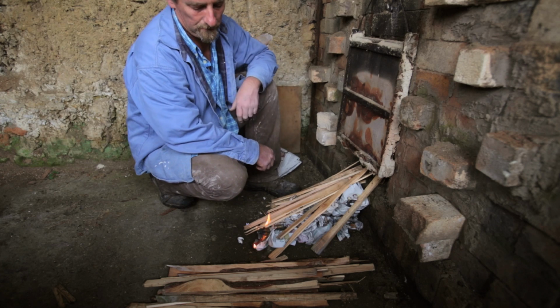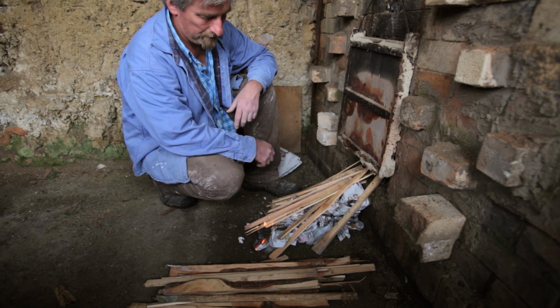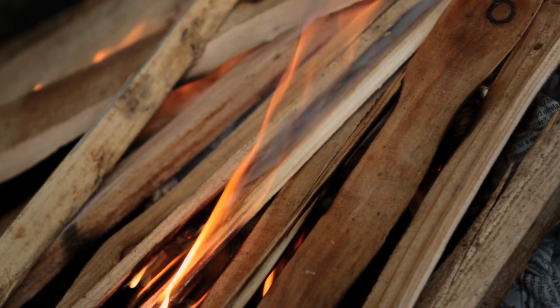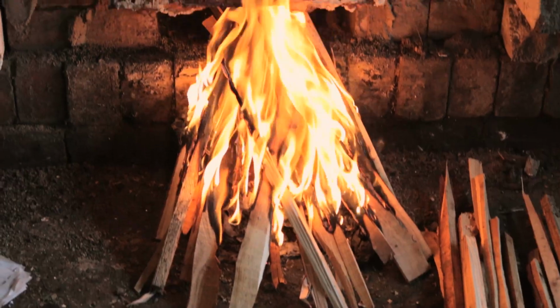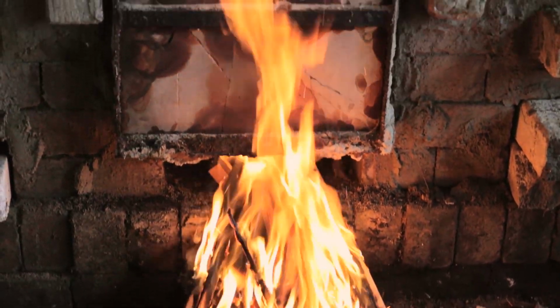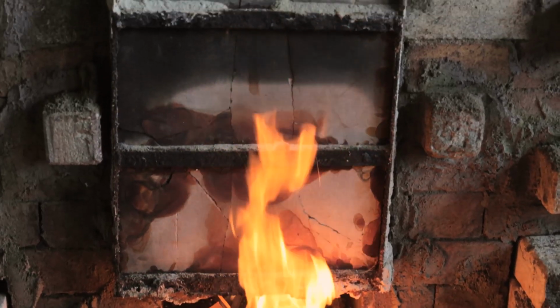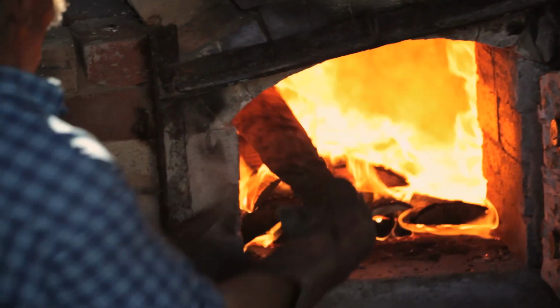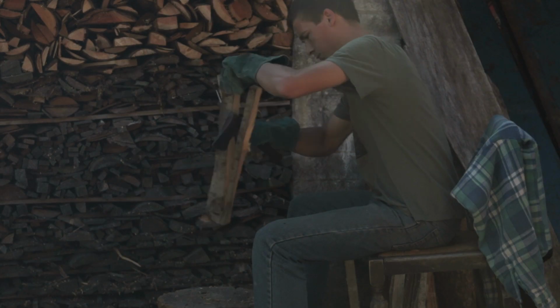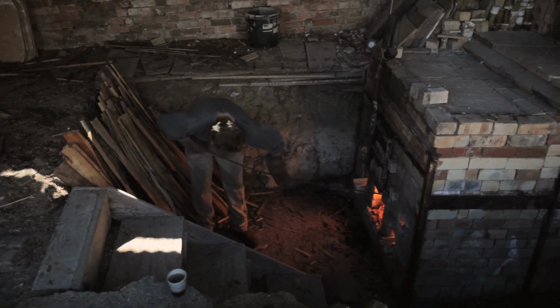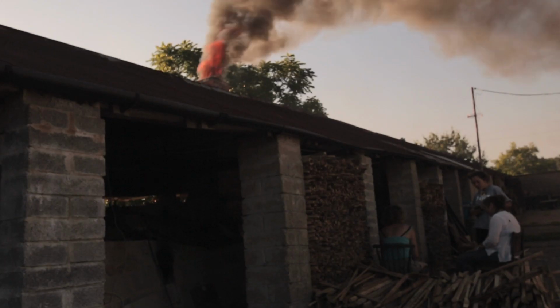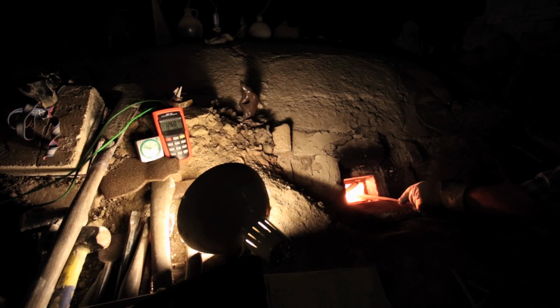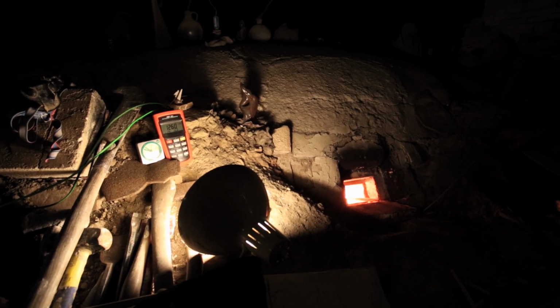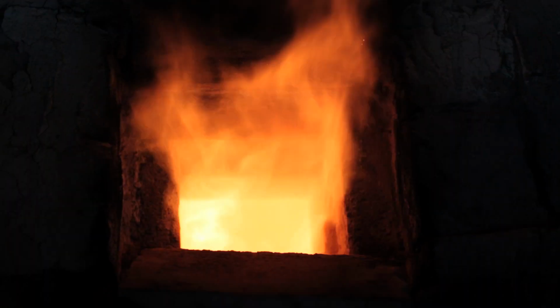So it's a very, very gentle fire for the first 12 hours, probably up to 400 degrees in that time. Then once we see colour in the kiln at about 500 degrees, we're able to push on with the stoking, adding more wood, more regularly, trying to build up a rhythm. By about 36 hours, we're at near on 1300 degrees, 1260 to 1300 degrees.